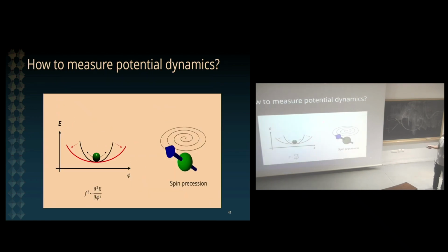And I already explained this, but I need to add an extra ingredient to the experiment. We want to be able to probe an evolution of the magnetic potential that I showed before over time after we excite the lattice. How can we do this? We know that the curvature of this potential will be reflected by the oscillation frequencies of our spins. This was discussed very nicely yesterday. So if we can track spin precession over time when we excite the lattice, we in principle have a way to probe the curvature of our magnetic potential.